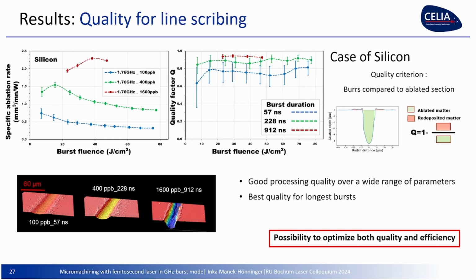So what is happening when you look at lines? What you can see here is, once again, the specific ablation rate. You see the same trend. I kept the colors. The quality factor is defined as 1 minus the redeposited matter in ratio to the ablated matter. So this is what is ablated. This is green. That's what we want. And what we don't want, put in red, the redeposited matter. And you can see the quality increases with the burst duration. So you have the best quality for long bursts. Here you see the redeposited matter doesn't really increase, but you get much deeper lines. This is what you can see here. So here you have both quality and efficiency optimized for the same parameter, luckily.